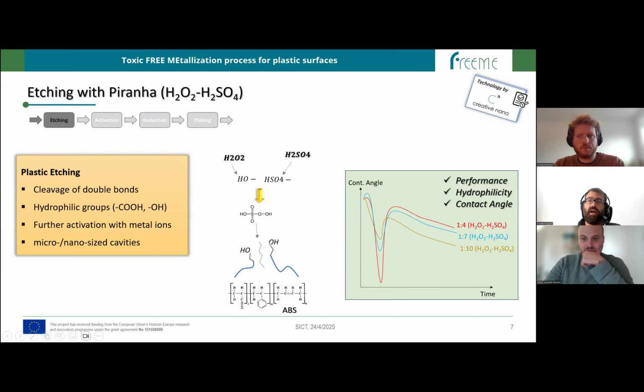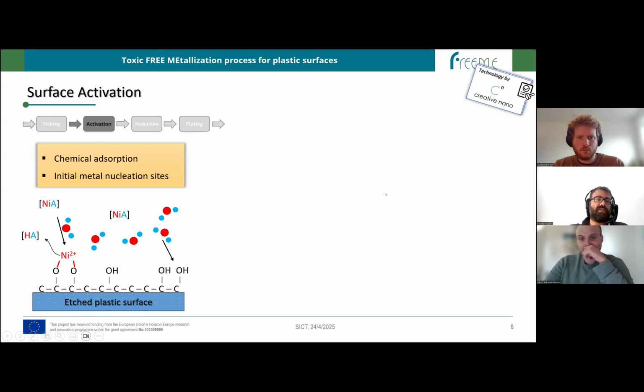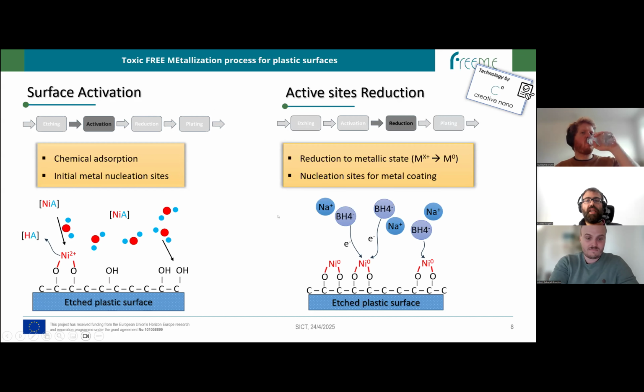And as a result, hydrophilicity is a metric of the performance of the etching process. And actually one property which can be used in this case is contact angle. And actually contact angle is the first property that will be modeled in this work. Secondly, we have the activation, where here you can see the hydroxyl groups from the previous step on the surface. And by using a nickel salt bath, we chemically adsorb the nickel ions on the surface, while next we are using the sodium borohydride mixture for the reduction of the nickel to metallic state. And actually we are developing the actual nucleation sites where the metallization procedure will initiate on the surface.